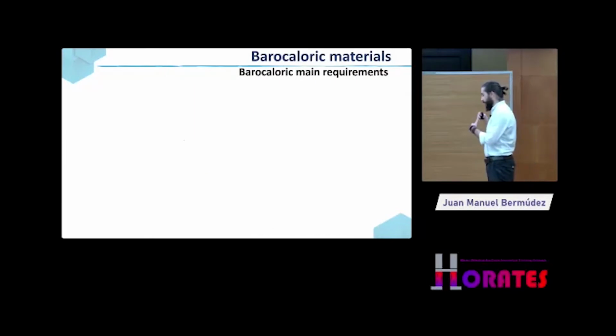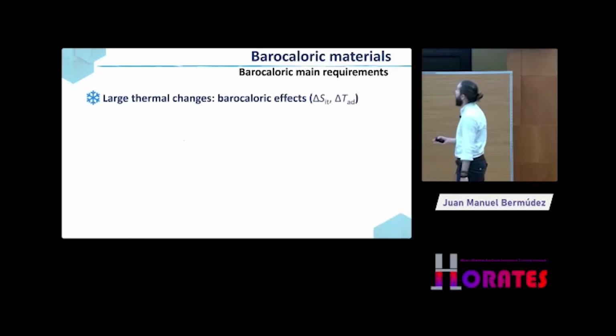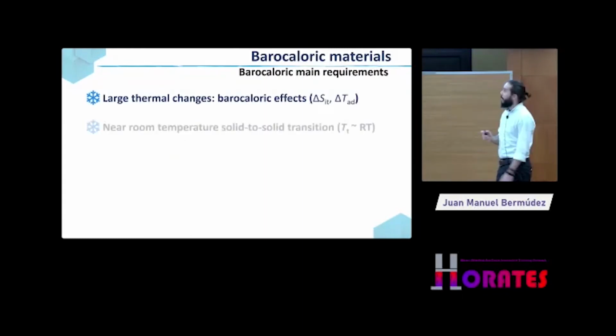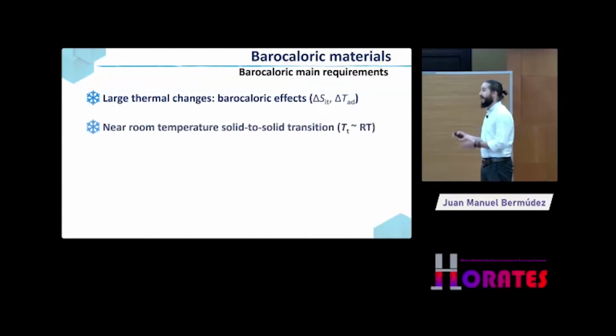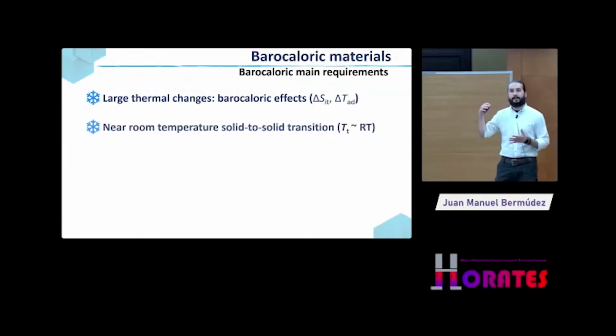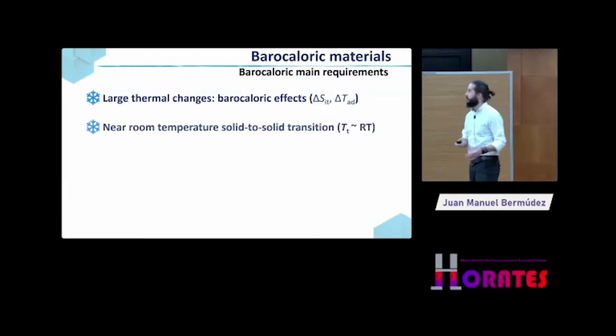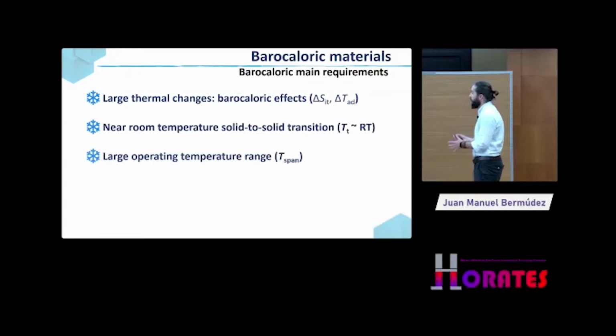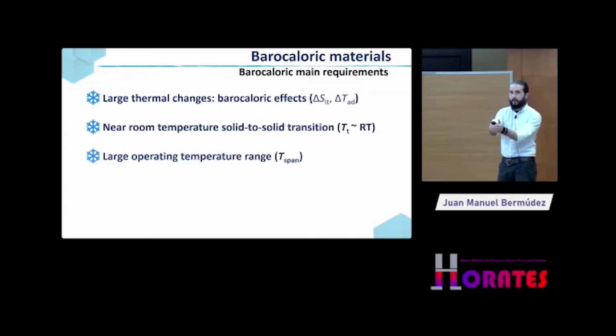Well, so for a barocaloric material, in order to be a good refrigerant, it has to have very large thermal changes or barocaloric effects, but also this material has to have the solid-to-solid phase transition near room temperature. And that is quite obvious, because if we are going to implement them in a fridge, the fridge is going to work at room temperature. So we want this phase transition to be able to be induced under room conditions, right? Then, on top of that, we want this material to not only work at 25 Celsius or 20 Celsius, but to work in a wide range of operating temperature, which is called temperature span, because the climate varies a lot across the world and across the seasons, so we want this fridge to work in winter and in summer and in north of Spain, south of Spain, in different areas, right? So we want a material that can adapt to the different climates.